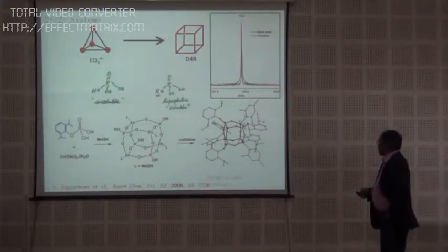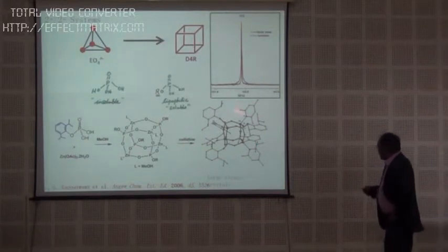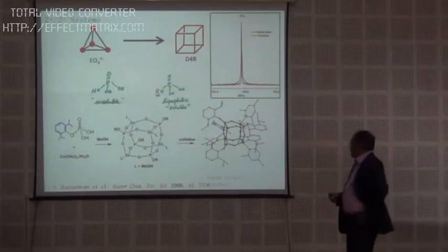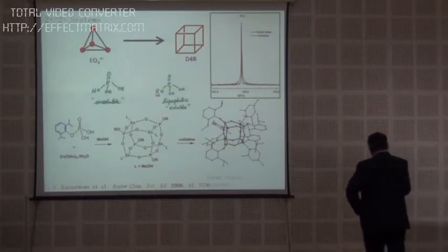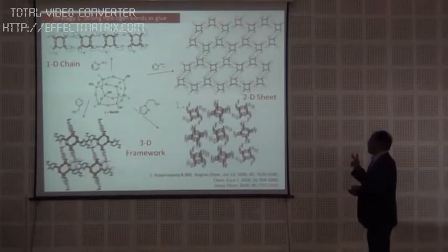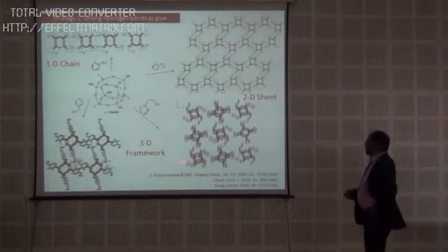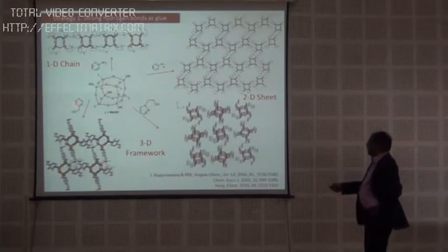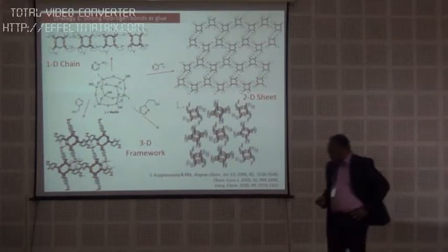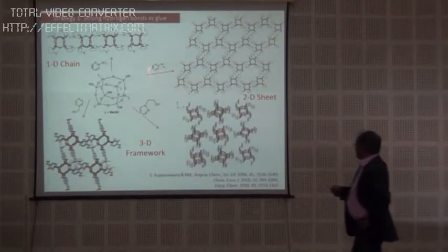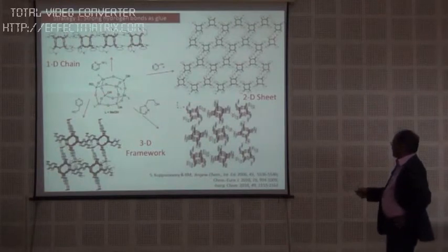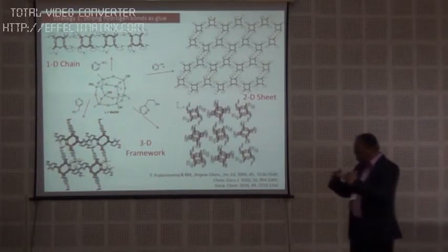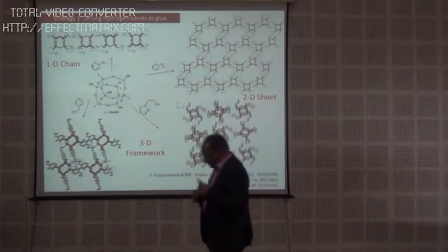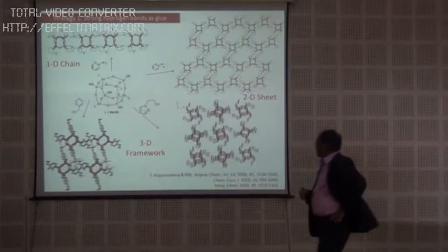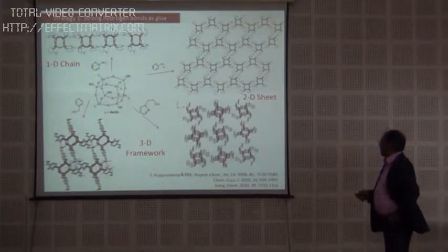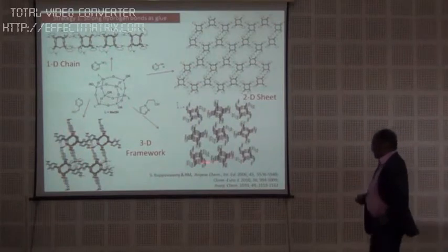Again, I'll cut a long story short to show that we used this building block and used several chemical linkages that we know of, namely hydrogen bonds and covalent bonds, and made a variety of porous structures. I will only show a couple of examples. This is one of our early works, about 10 to 12 years ago. We published it as a communication. We showed that you can simply use pyridines which contain additional functionalities like amino or phenolic moieties, or even methanolic, ethanolic moieties, as the source of forming hydrogen bonds between the cubanes. We actually engineered the number of what I call intra-cubane versus inter-cubane hydrogen bonds and built either a railroad, or a honeycomb, or even 3D structures.